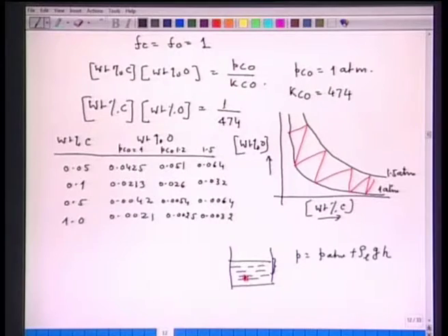So, if the nucleation of C plus O equal to CO bubble occurs deep in the bath, then on account of the ferrostatic pressure plus atmospheric pressure exerted on this bubble, the dissolution of oxygen in the bath increases.